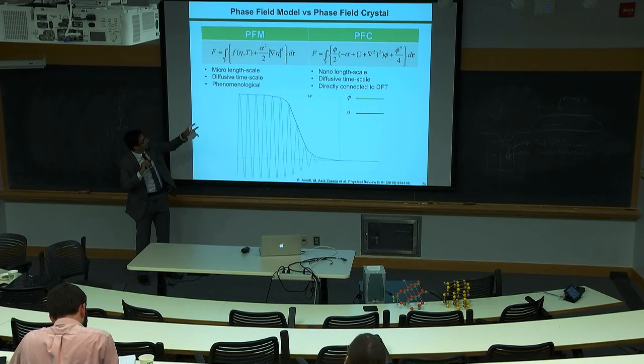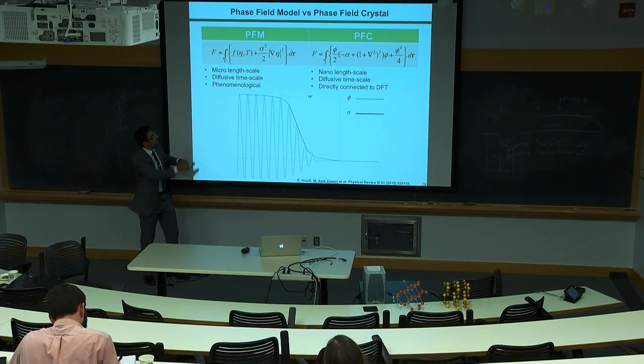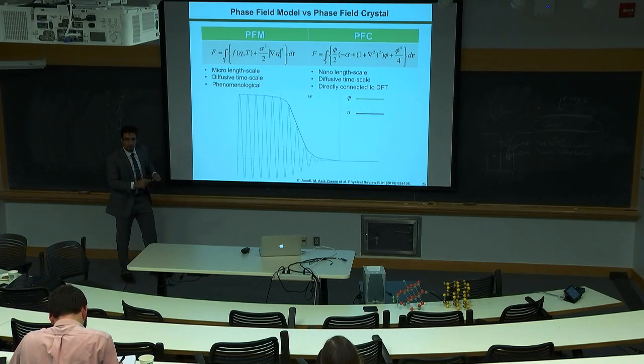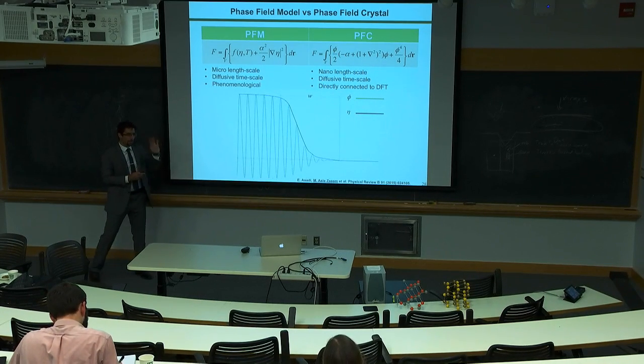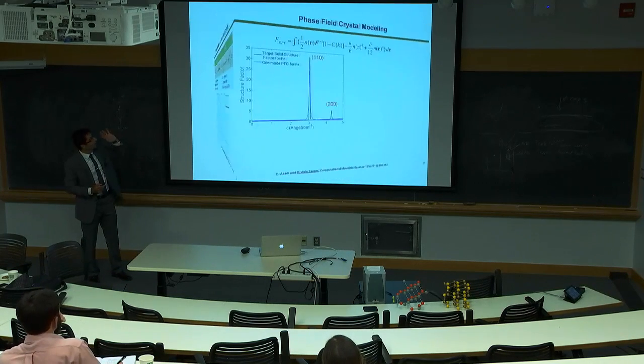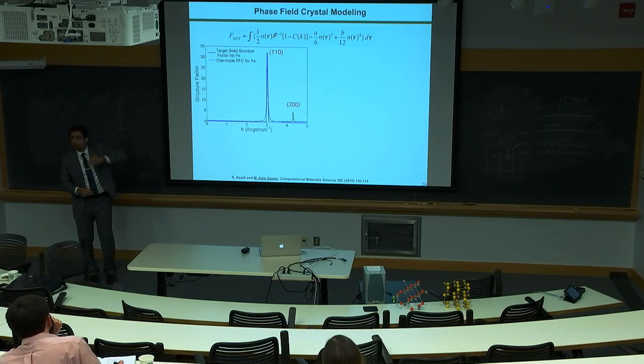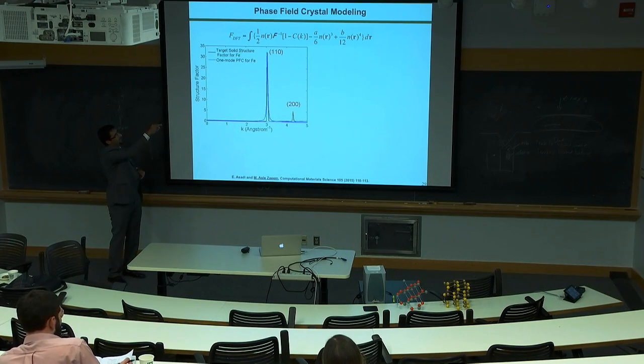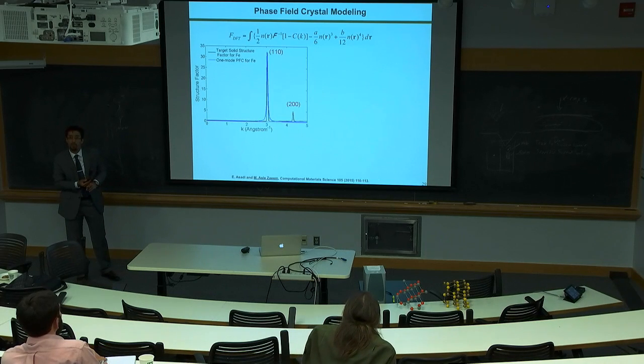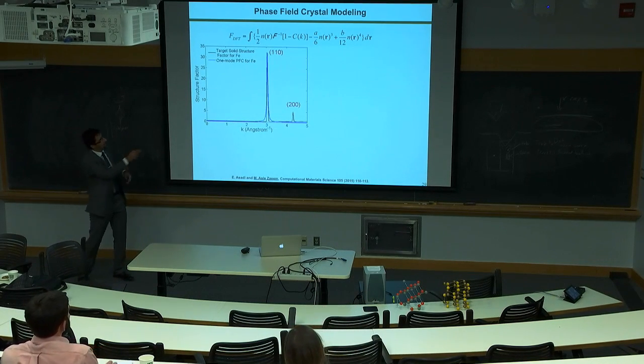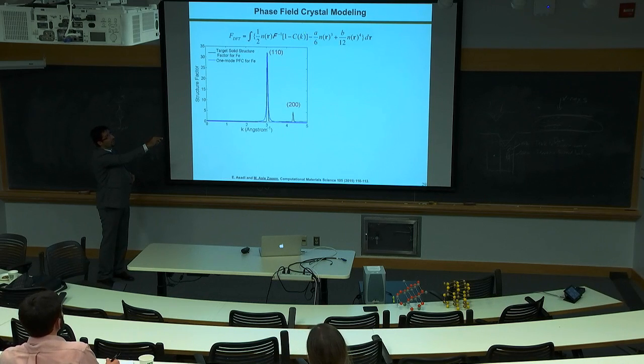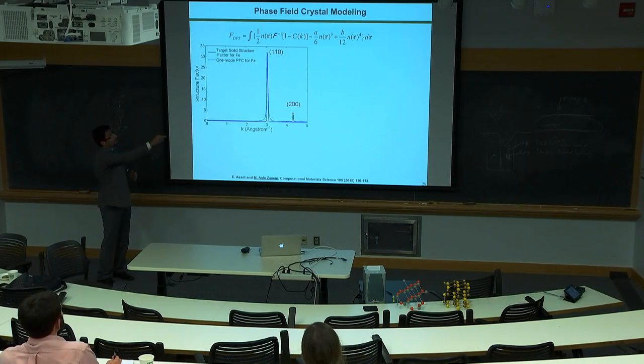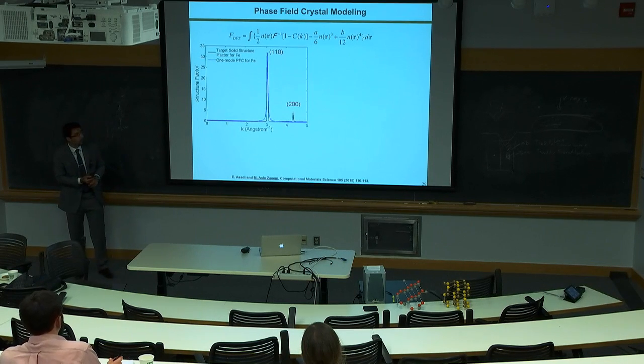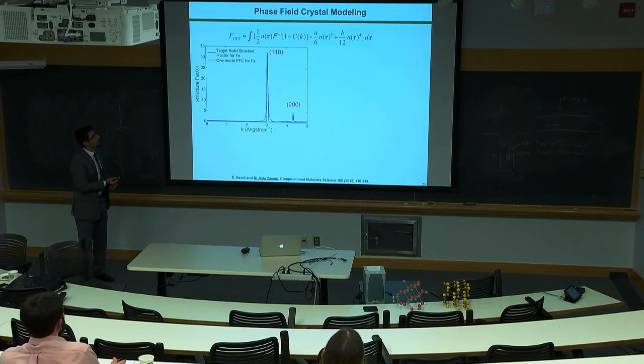Since I'm here, this eta could be concentration or any other kind of orientation field variable. Here, phi is the density field in phase field crystal. It's always density. It comes from density functional theory, and basically it's a free energy functional derived from density functional theory. This is a simple version of the free energy functional of density functional theory. You probably have seen this formulation somewhere. This is the correlation function in K space or Fourier space. And this is the backward Fourier transform, so it will become real space. But this is discrete, so I'm going to talk about it very fast.